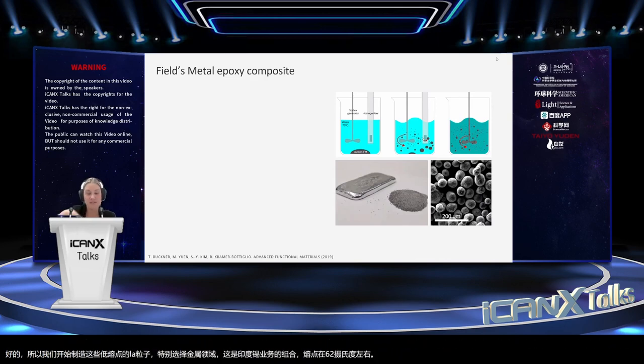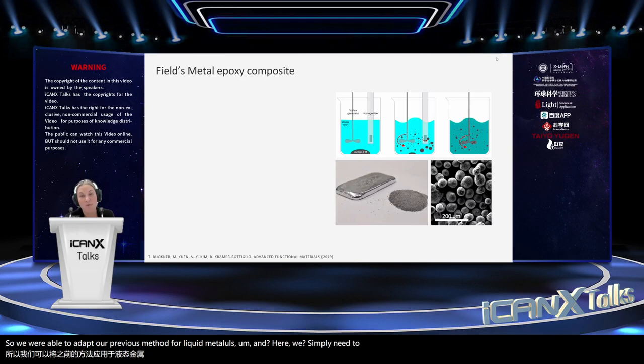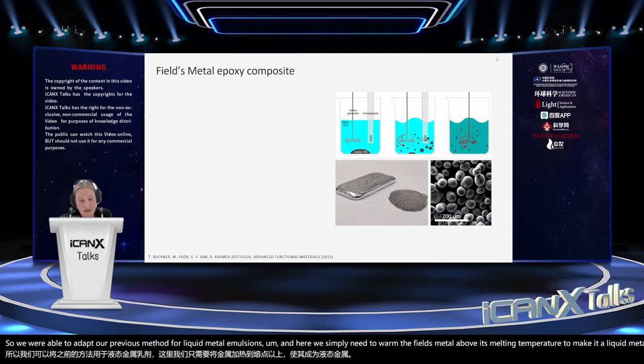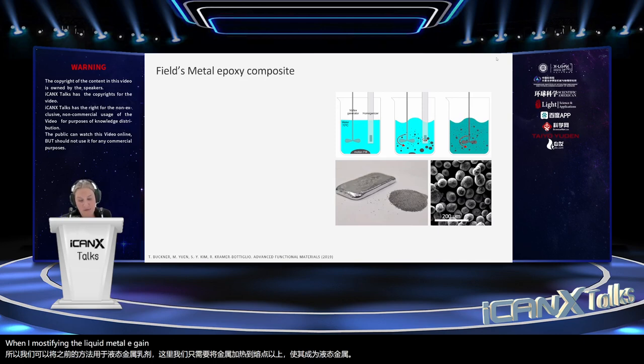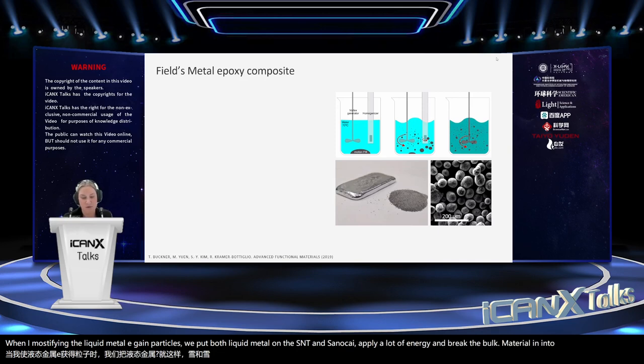So we were able to adapt our previous method for liquid metal emulsions. And here we simply need to warm the Fields metal above its melting temperature to make it a liquid metal. When emulsifying the liquid metal EGaIn particles, we put bulk liquid metal in a solvent and sonicate, apply a lot of energy, and break the bulk material into small particles. The longer we sonicate for, the smaller the particles.